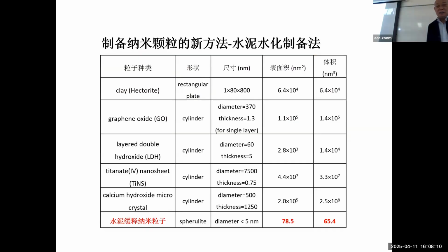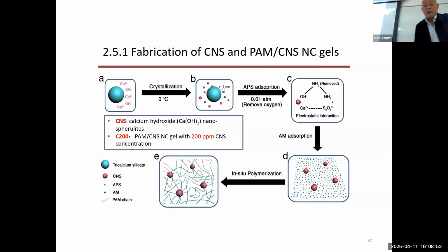So someone asked, if you got this, do you have any big advantage? So we compared with the other nanoparticles here. We found the surface area is the smallest, and the particle volume is the smallest. That means, for the same volume, we have more of these cement-produced nanoparticles. More particles have more effect in restraining or reinforcing the material. So we utilize these generated nanoparticles.